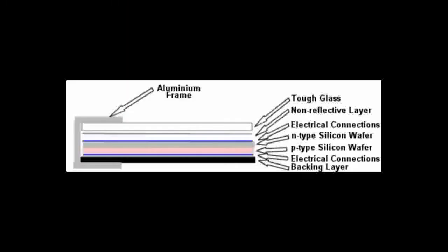What was it that bedeviled, I guess, the early panels was really a delamination problem and a condensation problem, where a panel's made with a glass front, and then you have your silicon wafer behind that, and then on the back you'll have some sort of protective backing, like a Tedlar, or you could even use glass, so some sort of plastic back there.